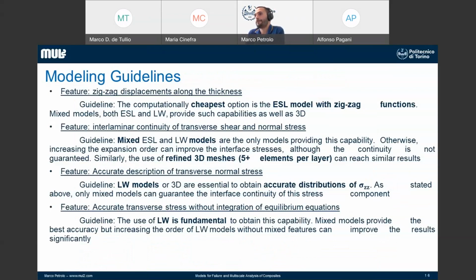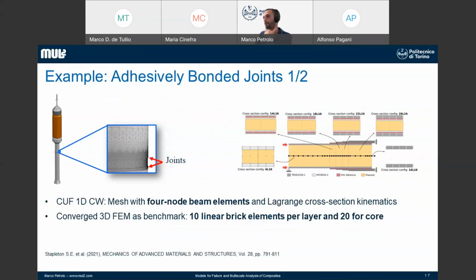In this slide, you can see a few models that we have available for modeling the different scales. We go from the equivalent single layer model, which is the most efficient from a computational standpoint, but is usually good enough for the macro scale. If you want to model the mesoscale, you need at least a layer-wise model. Layer-wise means that you explicitly model each layer with its own set of unknowns. This means a higher computational cost, but you get a very accurate stress field. And then so on up to the component-wise approach, in which you can model each single component at the microscale. Again, I don't go too much into the details of this. If you like, we can talk about this later, or you can contact me for that.